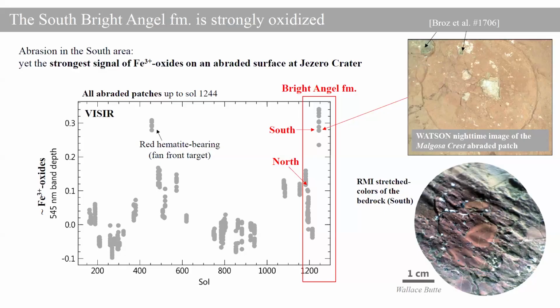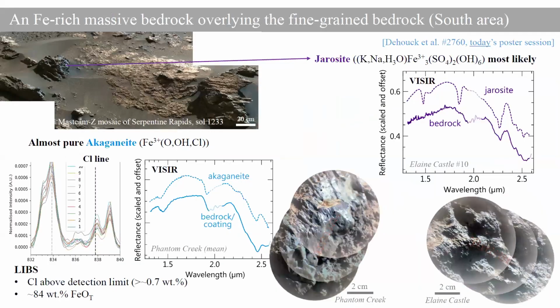Now going to the next slide, you will see that the southern region gets even more interesting as we looked in the upper part of the stratigraphy. Here we observe some iron-rich compositions, and the VISIR spectra are consistent with jarosite. You can see on the right that most of the diagnostic bands are present. And when we targeted further to the left, we had from VISIR and LIBS a very clear, almost pure detection of akaganeite, so chlorinated iron hydroxide. So with very high iron content and presence of chlorine. And if you want to learn more, Erwin Dehouck has a poster today on this exact topic. So next slide, please.